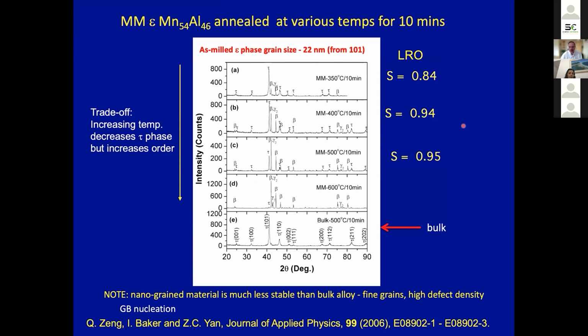So this is some cast material that was broken up and then mechanically milled and then annealed to go from the epsilon phase, which is the cast phase, to the tau phase. And this is X-ray diffraction data at increasing temperature, and down the bottom is for bulk material. If I start out with the bulk material, first of all, you can see this is a 10-minute anneal at 500 degrees C, and you've largely transformed to the tau phase in the material.